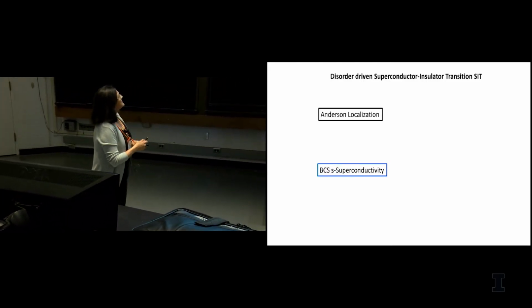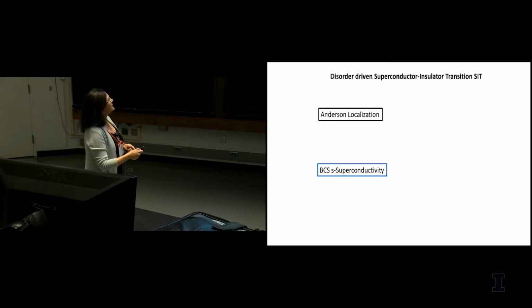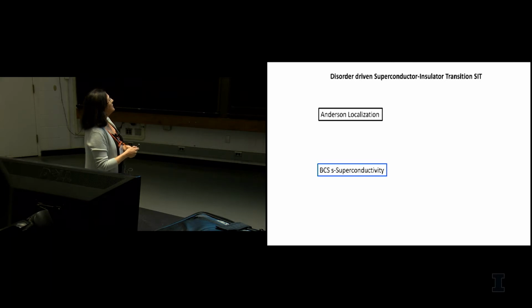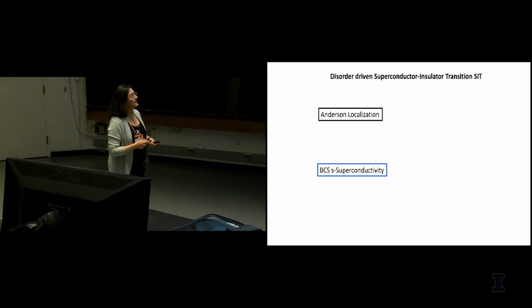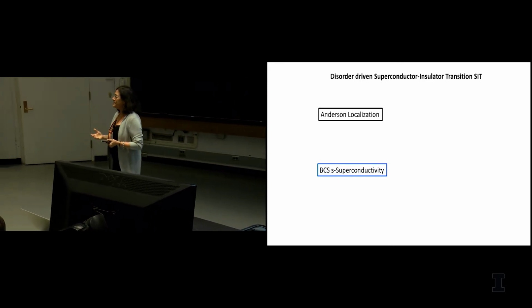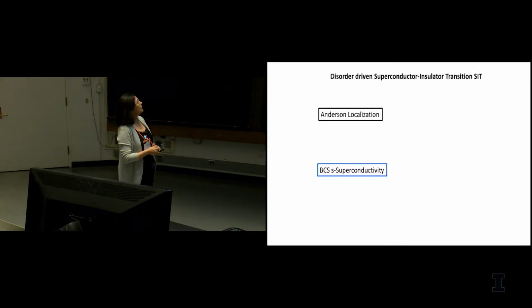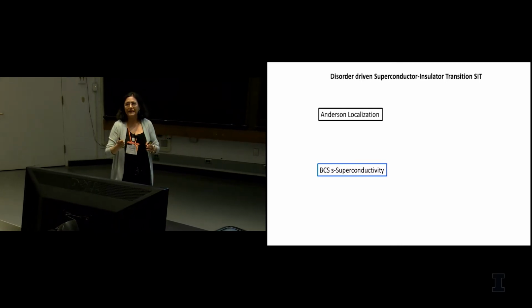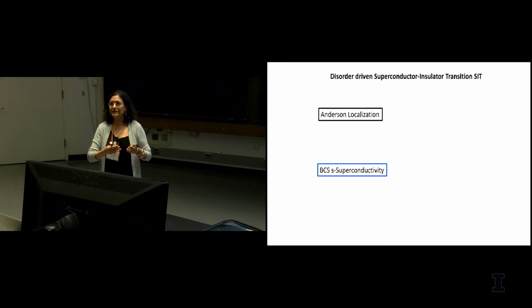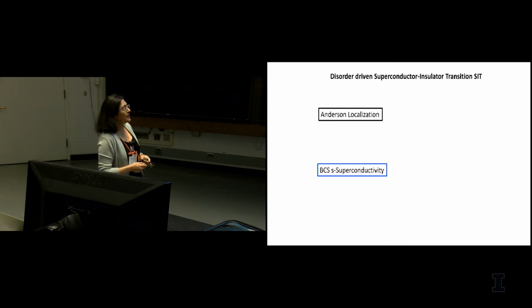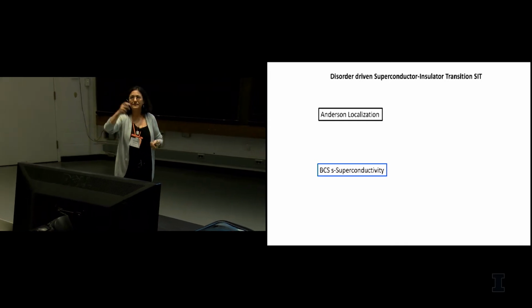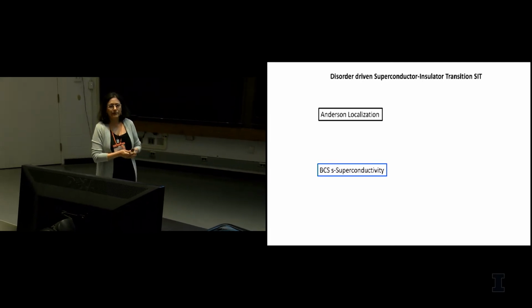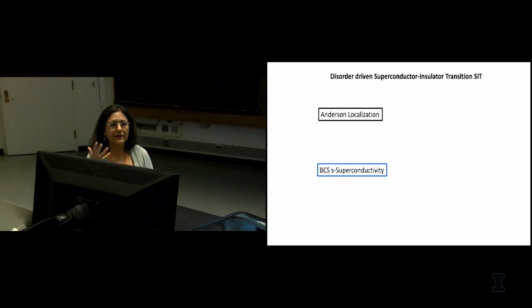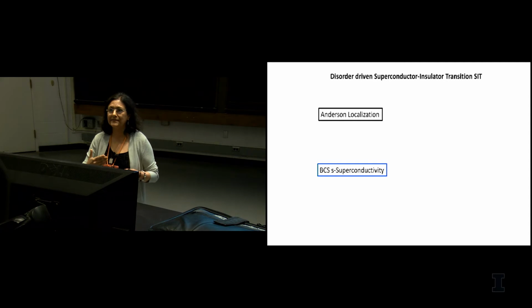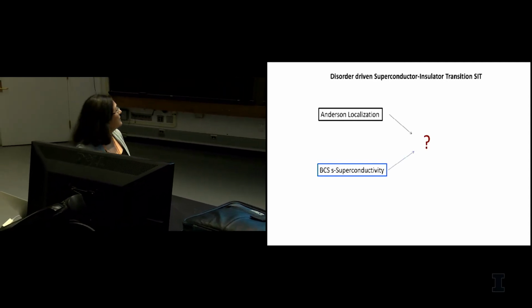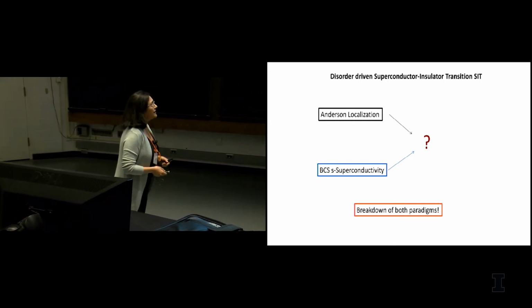So I'm going to start with the superconductor to insulator transition driven by disorder. We start with these two big paradigms. Anderson localization, which essentially describes disordered systems in the absence of any interactions. And we know by now how these behave. You get a mobility edge that separates metallic states from localized states, but there is no gap in the spectrum. So these are gapless insulators. You also have BCS S-wave superconductivity, where you have essentially the gap in the single particle spectrum, which controls the transition temperature. When you bring these together, rather surprisingly, I will show you both of these paradigms break down.